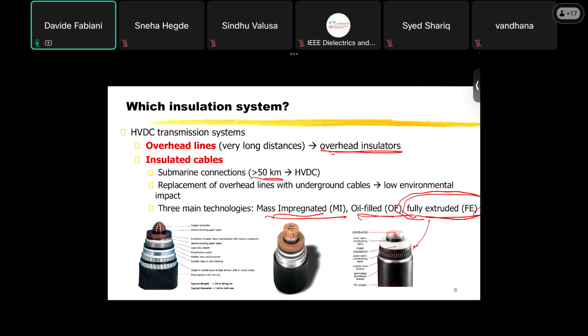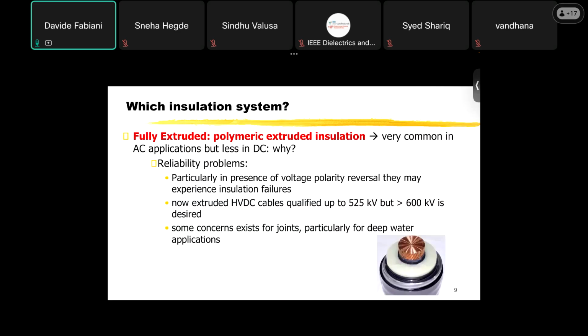But the problem is that fully extruded cables, which means cables with polymeric extruded insulation, even if they are very common for AC application, they were used for AC application since 1960, I would say, 1970. But for HVDC, up to, let's say, a few years ago, they were not the benchmark insulation system. Okay, so the reason for that, the fact that they were not so common for HVDC, is that polymeric insulation had some reliability problems if fed by DC.